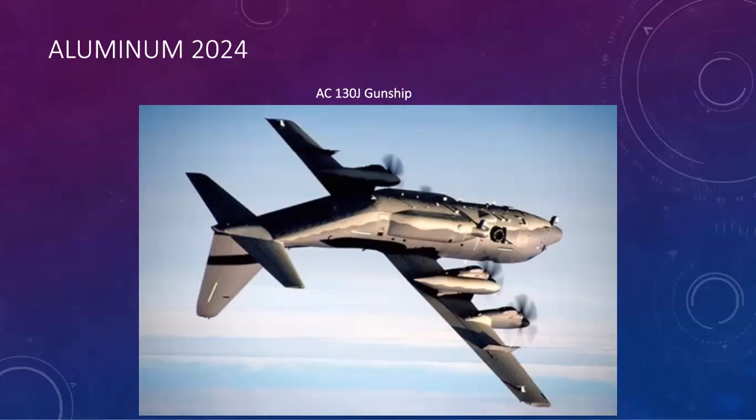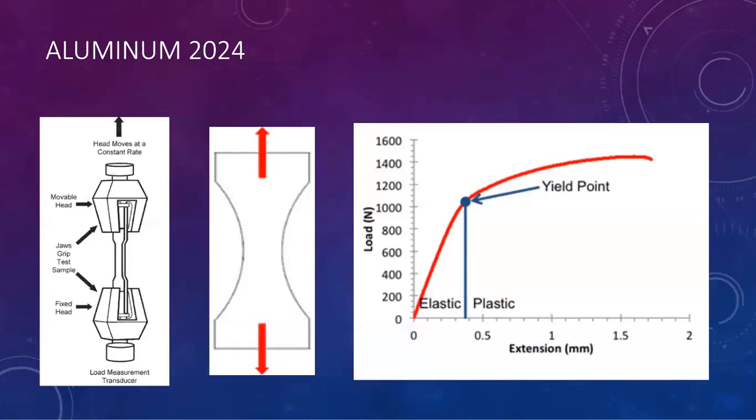So having a way that we could detect what's going on in our material if stresses cause it to go past the point of use is very important. So we specifically looked at a very low on the totem pole to get to that point. But we took some aluminum 2024 samples in the shape of this dog bone with this waist, and we put them into a one-time tensile tester. So we essentially had 2 clamps, we clamped it down, and we applied a set extension. When we do this, because of the shape of our sample, the stress localized at the center.